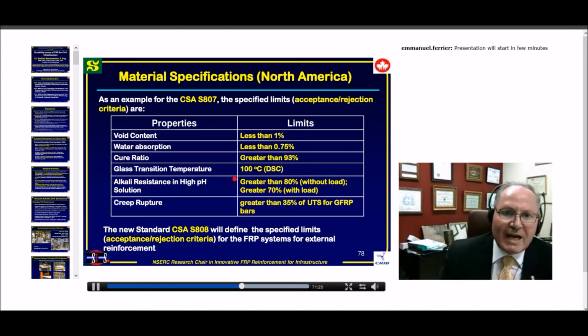Maybe some of you will ask where these numbers are coming from. When we started developing this standard, we based our analysis on the durability study that we did from the field. At that time, we were using mainly three products, one from Pultrall, one from Hughes Brothers, and another from Marshall Industries. Most of the bridges in Canada with rebar, we used these three bars, and we generated huge data in alkaline solution, without load and with load. We did really hundreds of tests here in Sherbrooke and also in some other universities.